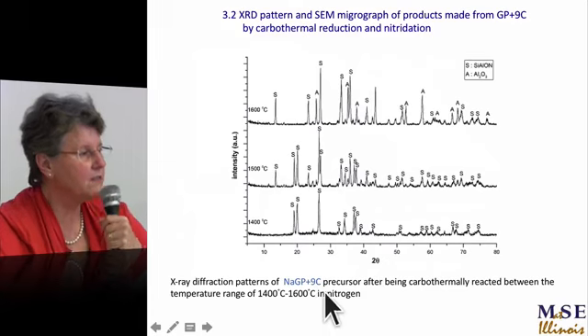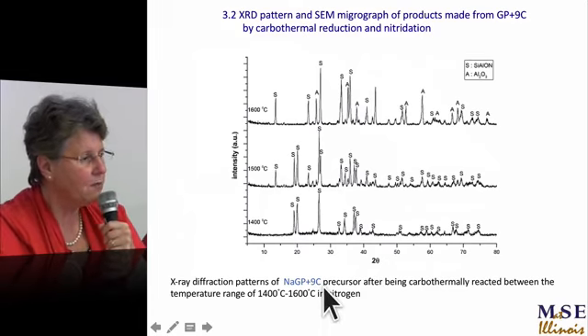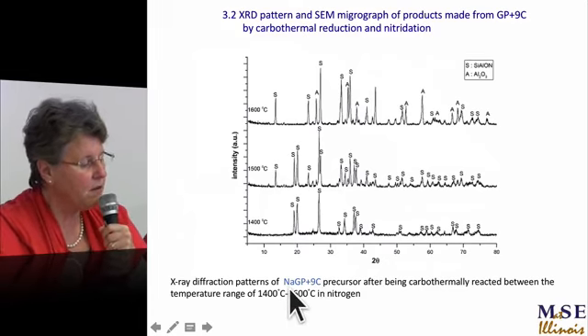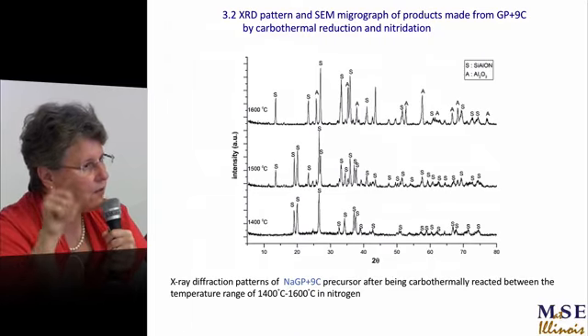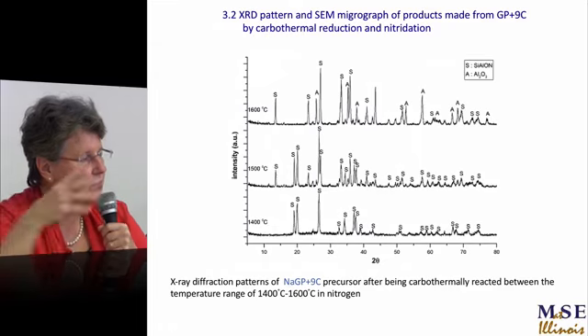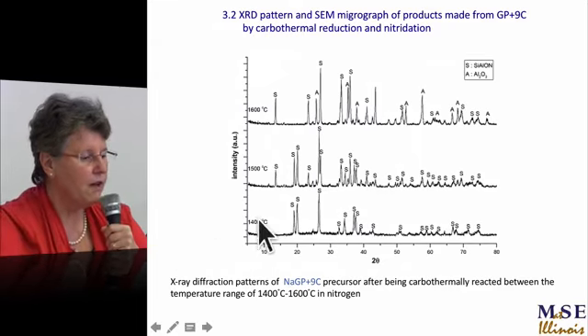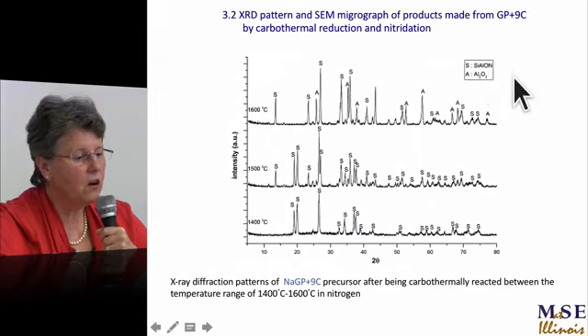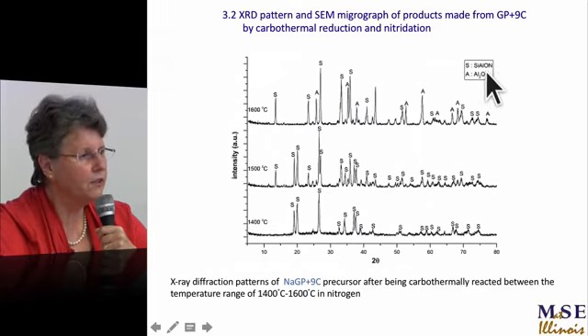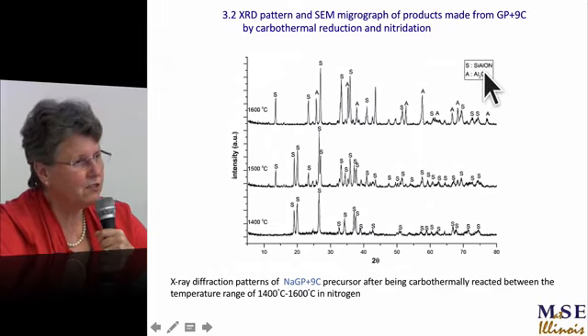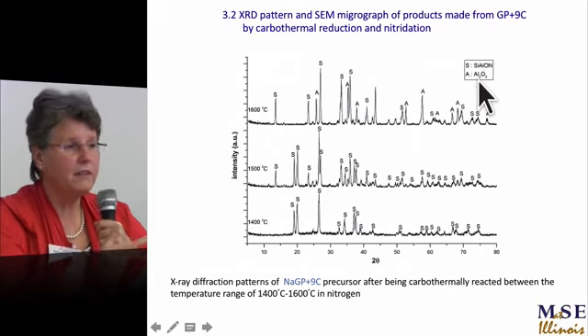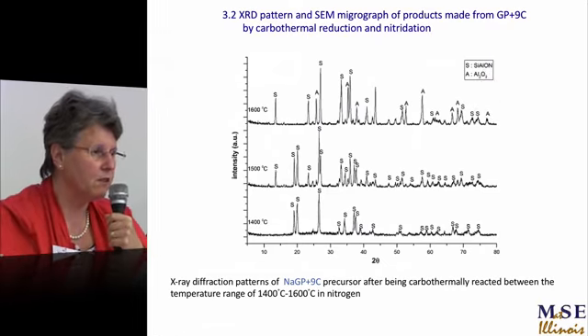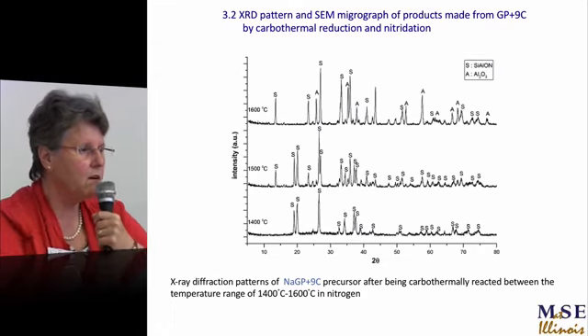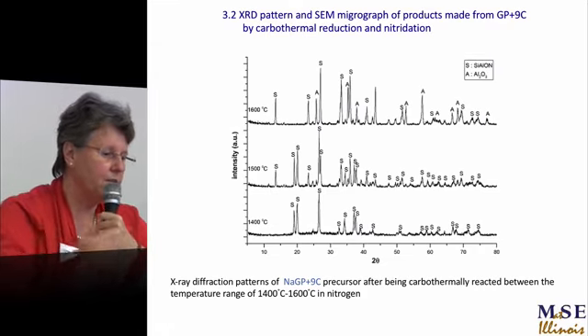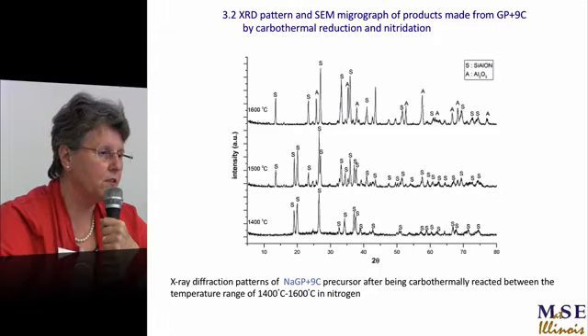Then the other one is, if you don't add so much carbon, just 9 moles of carbon, then you don't take away all the oxygen. Carbon plus oxygen equals CO2. Just put 9 moles, and then you start forming sialons, which is a pretty good high-temperature structural ceramic. It's already nano for you. You don't have to grind it. You just have to flow the gas over it, and then collect it.